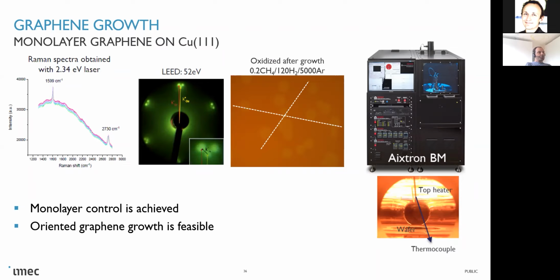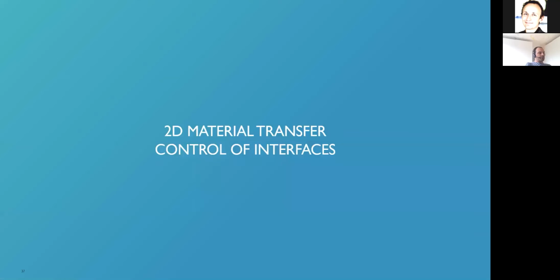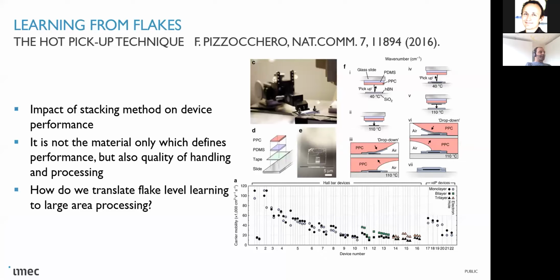So towards the growth, we think that there are enough opportunities to grow the single crystalline material. It's just a matter of time and engineering. But the next thing is the transfer and mainly the control of interfaces. And well, because I was invited by Peter, I wanted to refer to this paper on the hot pickup technique, where they are showing that it's extremely important the way you are manipulating the flakes, and you need to control the strain that you build up in the flake.